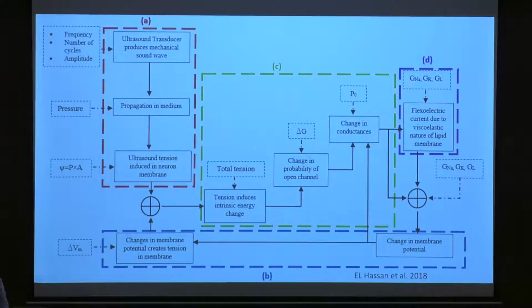So this is a summary of the three main components that exist in our model that are coupled with the Hodgkin and Huxley model. The red box shows the effect of ultrasound stimulation, which causes tension in the membrane. The green box shows that whenever tension comes into the membrane, it causes variation in the probability of the ion channels. It changes the energy difference in the membrane, which affects the probability of an ion channel, whether it's open or not. And this probability is what mainly controls the conductances in the Hodgkin and Huxley model.